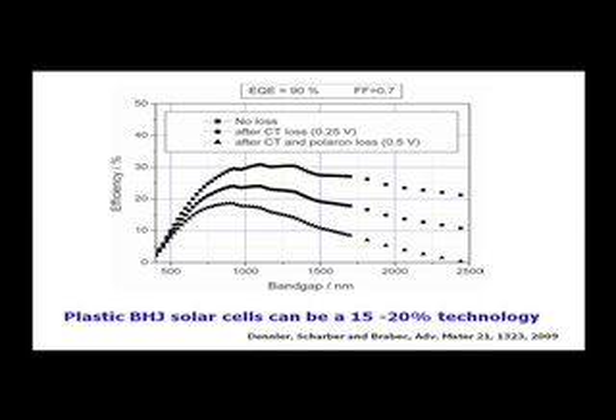This is as a function of the band gap. As I said, the band gap for silicon is about here. And indeed, if you make the gap smaller, you get more efficiency. And eventually you start losing because all the carriers relax at the bottom of the band. But it's an interesting number, it's 30%. Well, it's unrealistic. We can't ever make it that perfectly. But without trying to prove it to you, I honestly think we can get into this regime. And surely this one is accessible to us. So I'm telling you that I think we should be able to achieve polymer solar cells in the range of 15 to 20%, or maybe even higher. And I'll show you where we are in a minute.